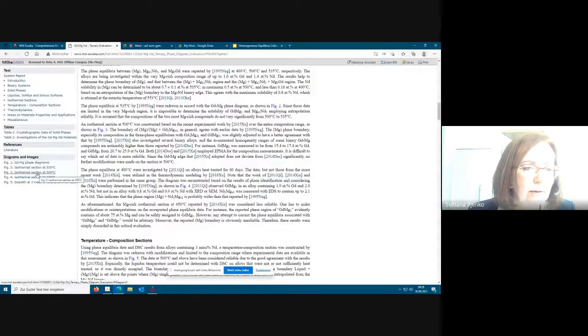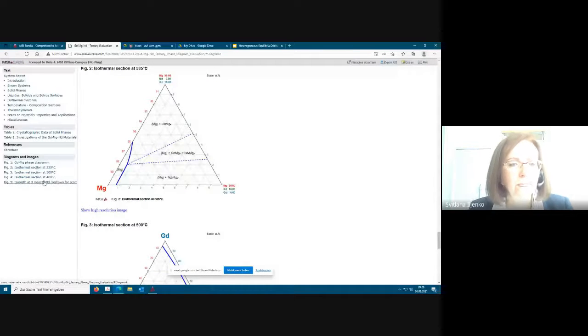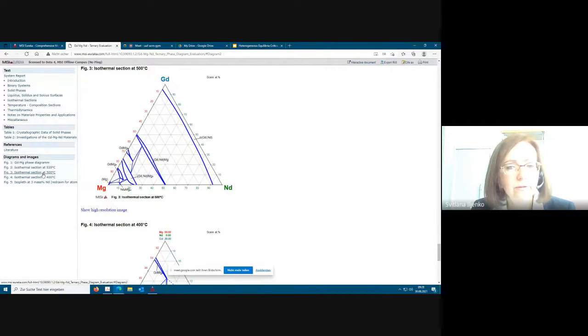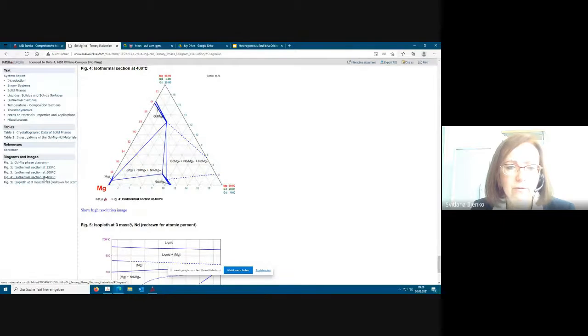And if we look at other isothermal sections which are presented here, for example, just 50 degrees above, the 500 section and the 400 degrees section, then we see that it's really rather unlikely that in this 50 degrees between these 3 sections, there would be another continuous solid solution. And in particular, if the phase doesn't exist, it also wouldn't appear there. Therefore, this section in this case was actually not included in the report.